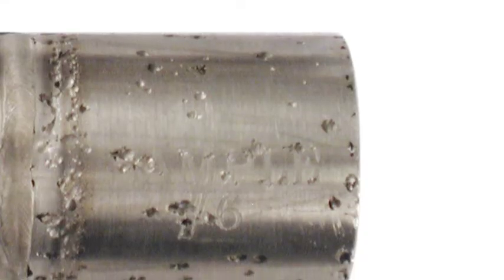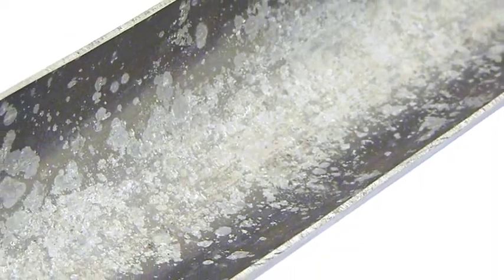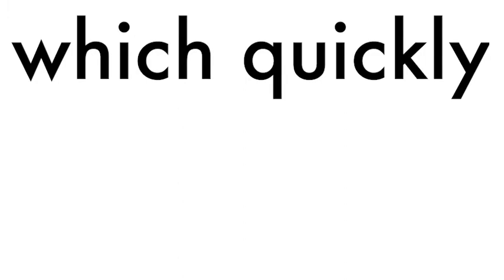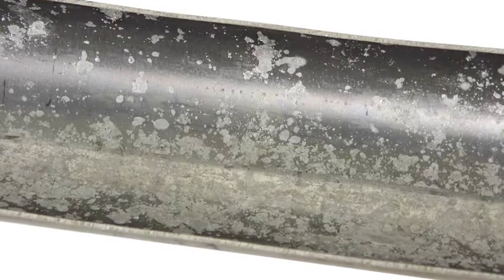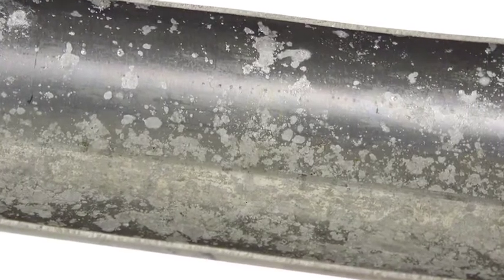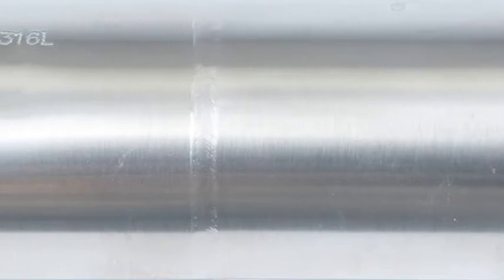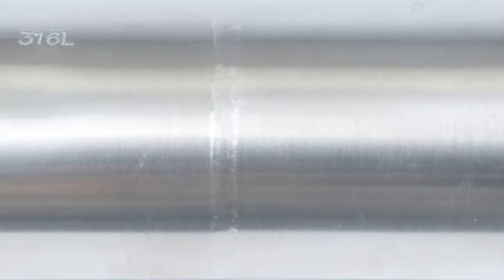Pitting is a type of corrosion in which chromium is dissolved in the chromium oxide layer of the metal. This leaves only the less resistant iron to fight the chlorides, which quickly bore into the steel, creating spherical pits in the material. The manufacturer replaced the piping for the second time with 316L.